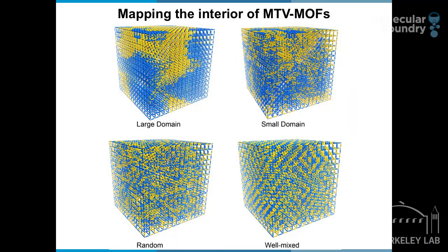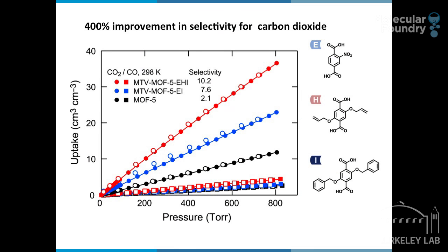Recently, in a collaboration with Bernd Schmidt and Jeff Reimer at UC Berkeley, we have uncovered that these functionalities apportion themselves so that they map the space within the crystal with specific functionalities. In this graph, you see in the yellow domain is one functionality, the blue domain is a different functionality, and they're arranged in either large domains, small domains, random, or well mixed, depending on which functionalities we use. This kind of chemistry essentially results in, when you mix functionalities and you apportion them in the proper way, we achieve 400% improvement in selectivity for carbon dioxide relative to the unapportioned or the unmixed material.